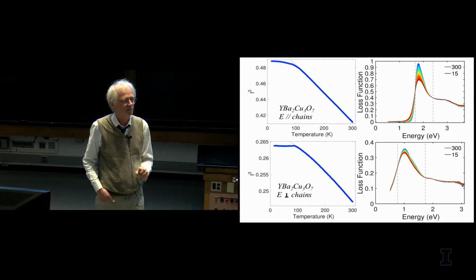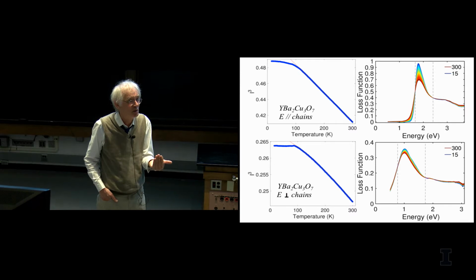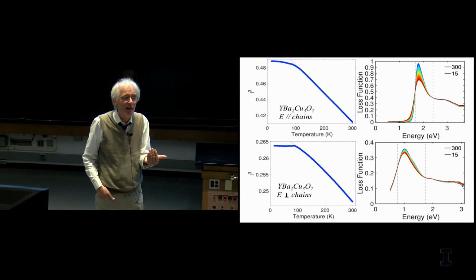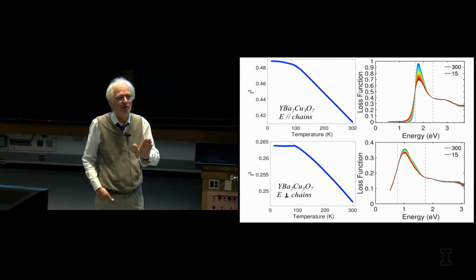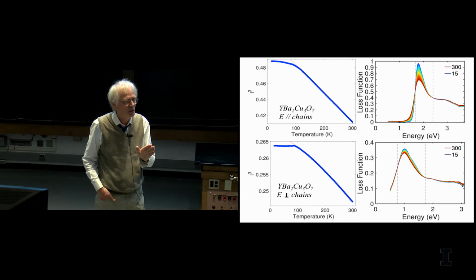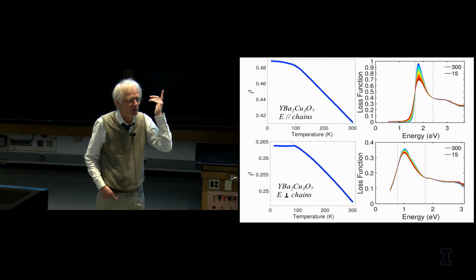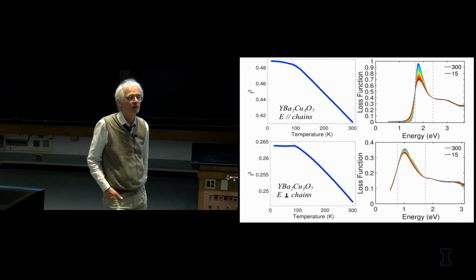No, I mean, is there some behavior? Well, yeah, there is some behavior in the sense that there is no plasmon in the normal state, and it is there in the superconducting state. So if you take that and you do the integral, you will probably find that the Coulomb energy increases going superconducting. But that's a very, very tiny amount. It's a factor of 100 smaller or so than what we actually see along the AB plane.